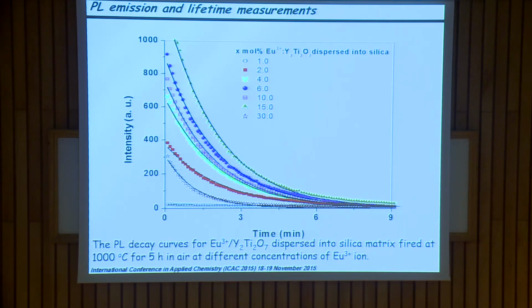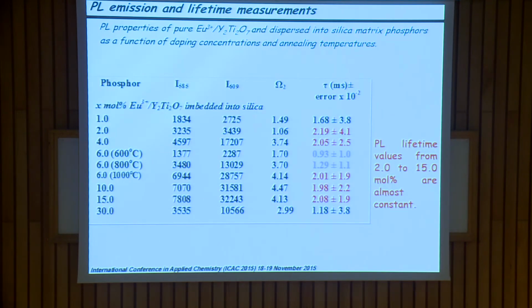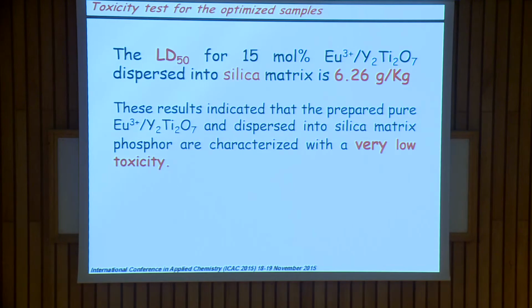And this is the photoluminescence lifetime decay curve. As we can see from the calculation of the lifetime, the lifetime is stable from about 2 mole% doping to 15 mole%. Also, to apply our material in the field, we should test the toxicity, and the LD50 for the high-loading europium equals 6.2 grams per kilogram, which is a huge amount. So our material is characterized by very low toxicity.